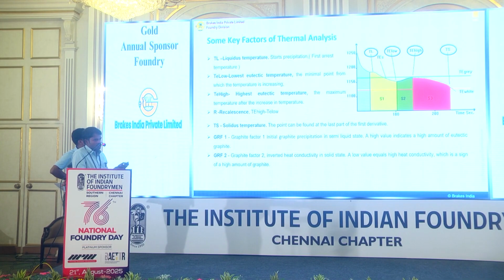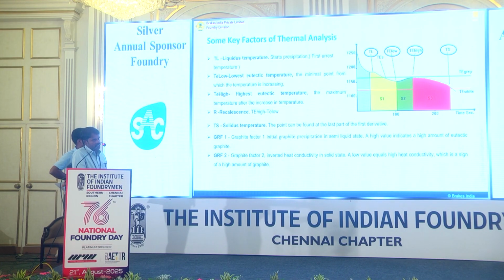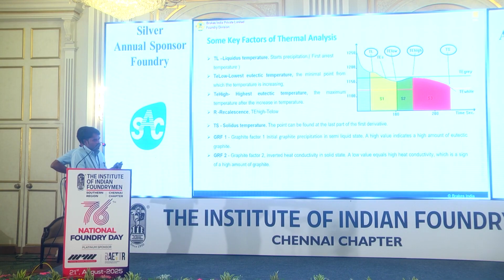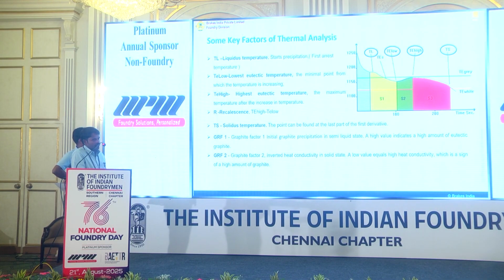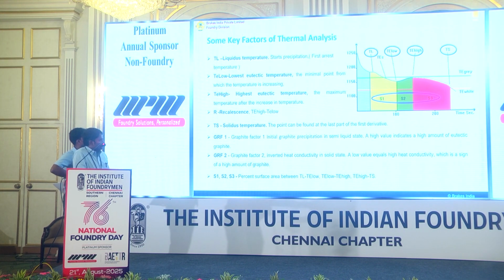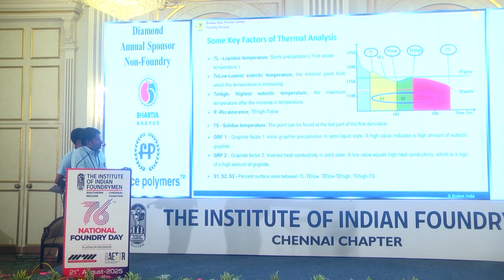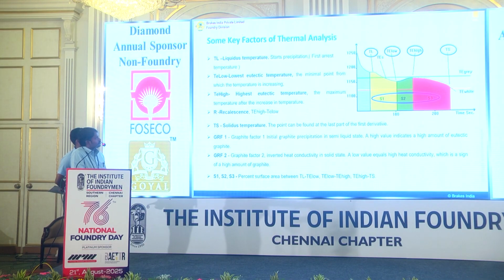And graphite factor 2 is nothing but the heat conductivity at the solid state. So a lesser value of graphite factor is a good sign and indicates a higher amount of graphite present in the metal. So S1, S2, S3, these three surface phases, are the difference between the liquidus temperature and eutectic low, and eutectic low and eutectic high, and the eutectic high and the solidus temperatures.